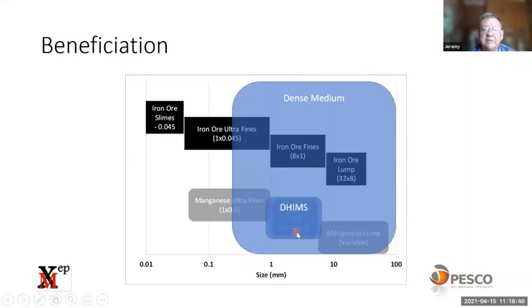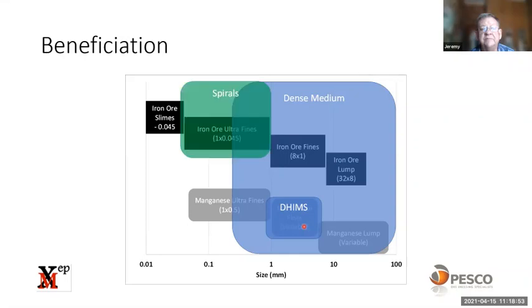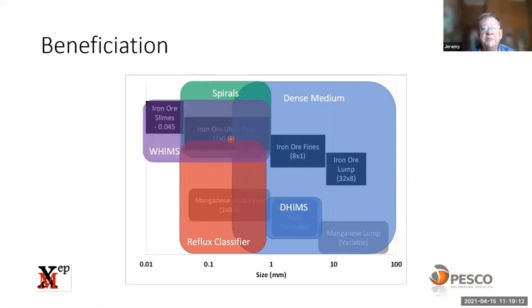If we look at dry, high-intensity magnetic separation, that's specifically applicable to the manganese fines, where we use the magnetic properties of the manganese and the host material to upgrade the manganese content. Then spirals. Spirals are typically focused on the 1 by 45 micron fraction. And then reflux classifiers also overlap to a certain degree or to a large degree with spirals in the same size range. And then you've got WHIMS, which is wet high intensity magnetic separation. And typically that's used on -1 millimeter ore. And it encompasses slimes as well. And then if you're looking at flotation, the flotation would be focused on the slimes.